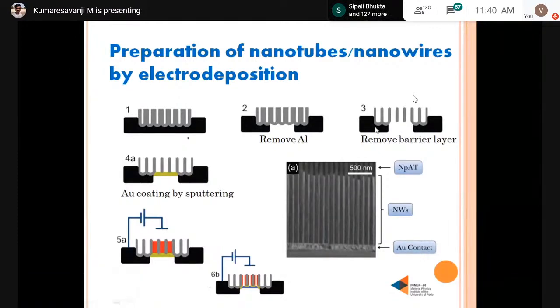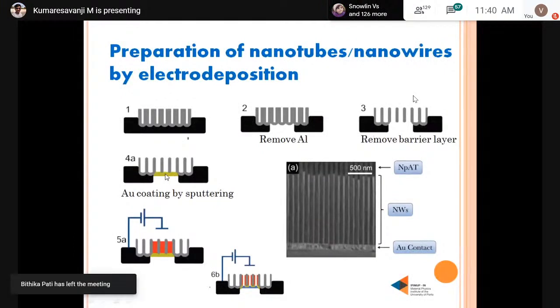Now we coat the bottom of this template with gold using the sputtering technique. That will act as an electrode, right? So now we fill in the electrolytes we require and we do the electrodeposition. By doing this, we can get nanotubes. Here I show some micrographs of nanotubes going from bottom to up.